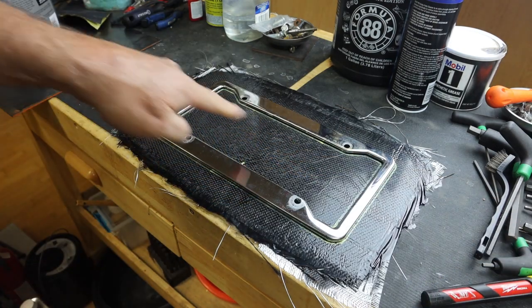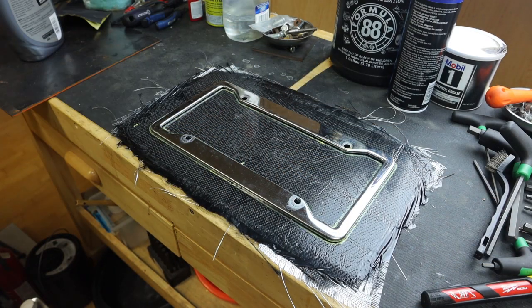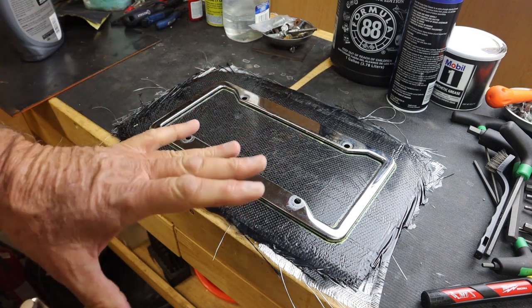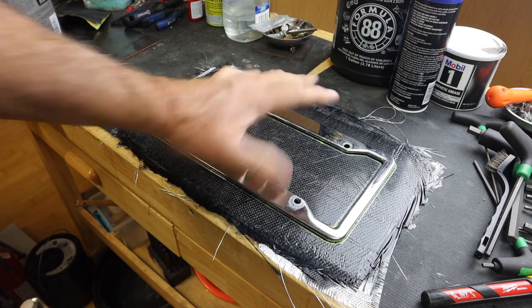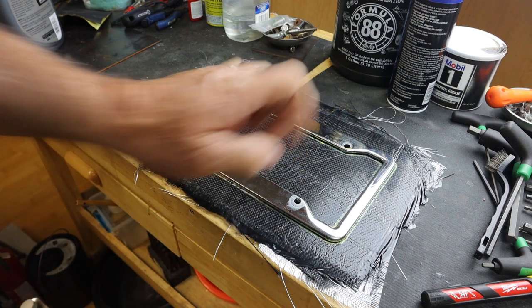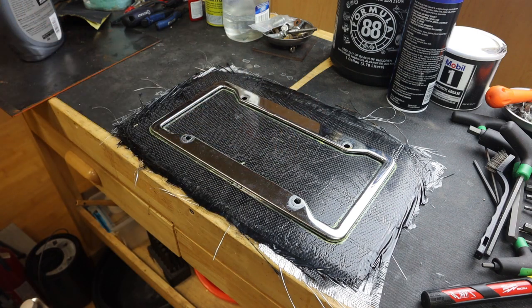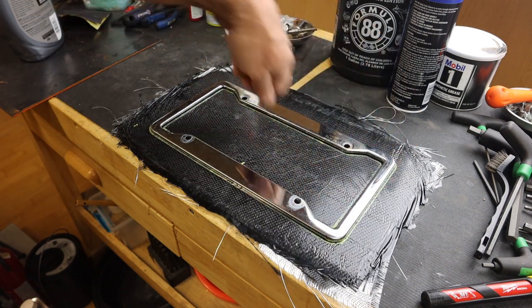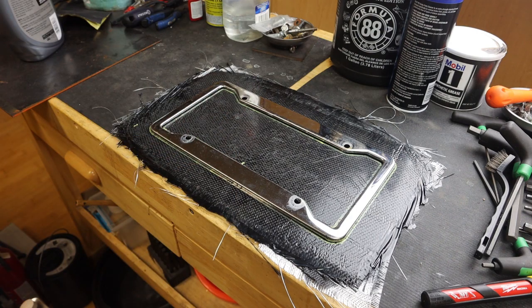One thing is, when you're cutting and drilling with carbon, the dust is very toxic. Make sure you wear a respirator. If you're going to use a Dremel tool, make sure you use the flexible shaft and keep the Dremel itself away from the dust area. Carbon fiber dust is electrically conductive, and I've shorted out several Dremel tools, so make sure you use a flexible shaft. Keep that Dremel protected, covered with a cloth or something to keep the dust from getting into the brushed area of the electric motor.